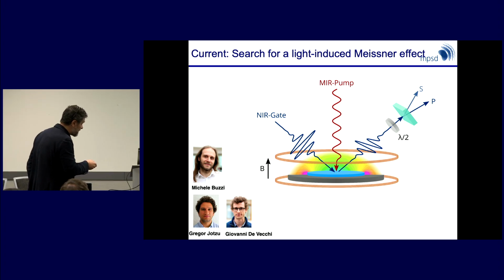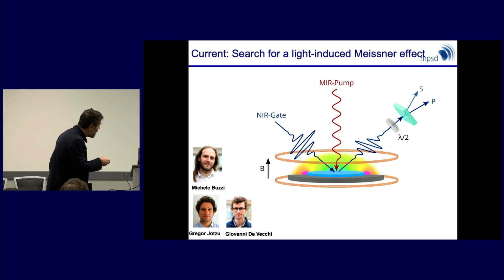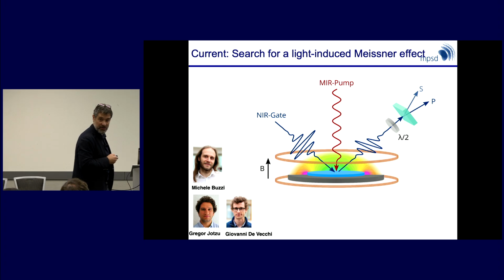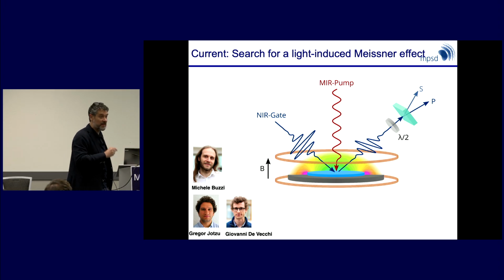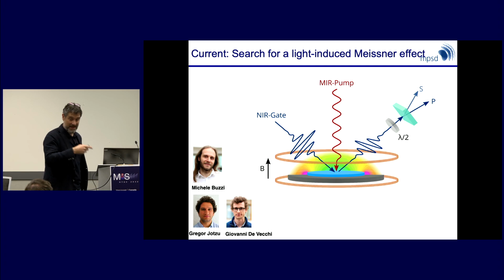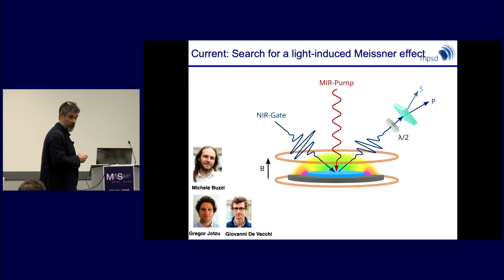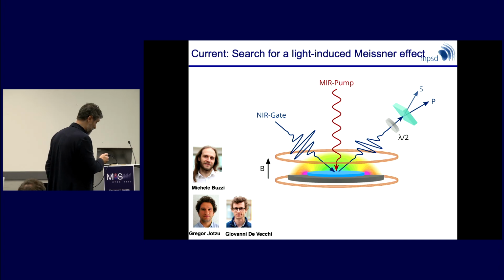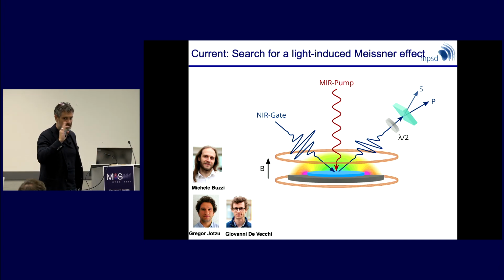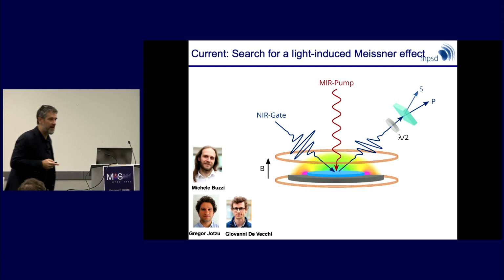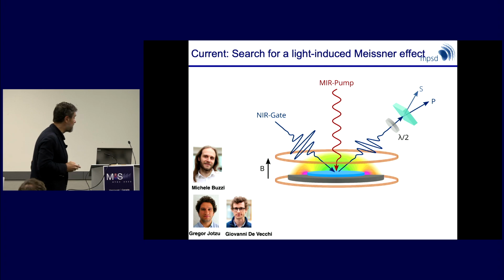The way they're trying to do the experiment is, if this is the C60, you can apply a field, and you can put a garnet here on top, in which you can use MOKE, the magneto-optical Kerr effect, to measure the local magnetic field immediately outside the superconductor, and now photoexcite the superconductor and try to characterize changes in the magnetic field immediately outside the sample. If the material does become a superconductor and it is a diamagnet, you should get a reduction of the magnetic field here and an enhancement here, because of expulsion. So this experiment kind of works on odd days and doesn't work on even days, and we don't entirely understand the observations, so I won't claim that this is done to any degree of confidence.